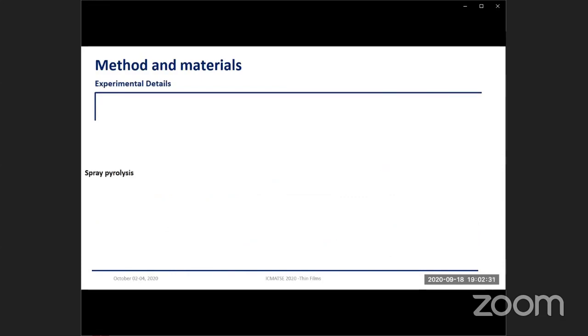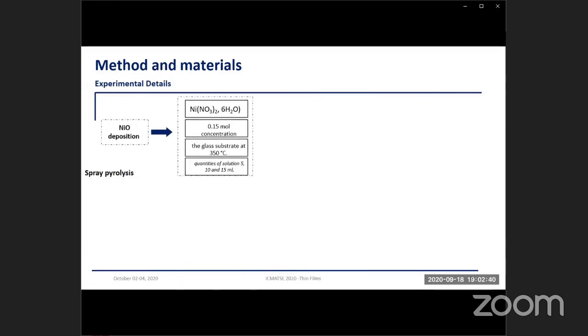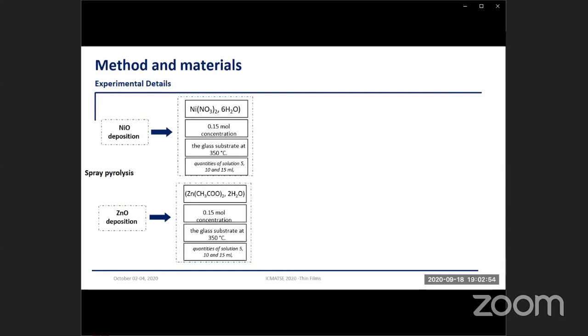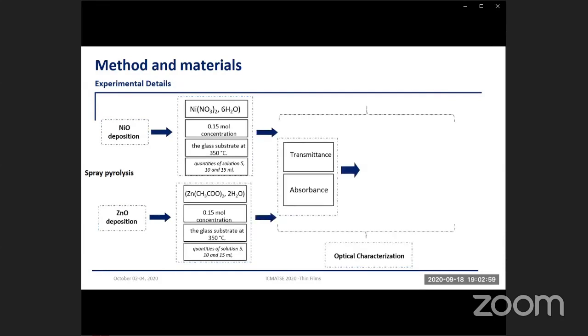Experimental details: in this work, by the spray pyrolysis method, nickel oxide films were grown on glass substrate with conditions of precursor, concentration, and temperature, for 3 different quantities of solution: 5, 10, and 15. Also, we did the growth for zinc oxide with the following conditions. Then, we did the optical characterization to extract optical parameters used in the simulation section.